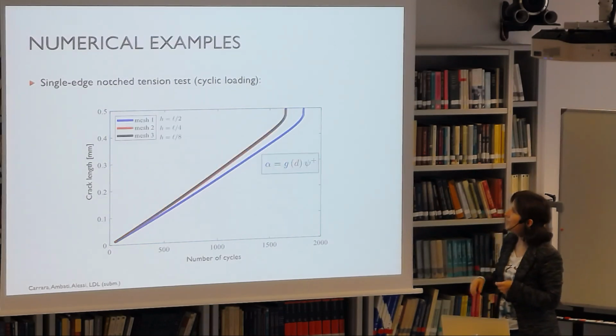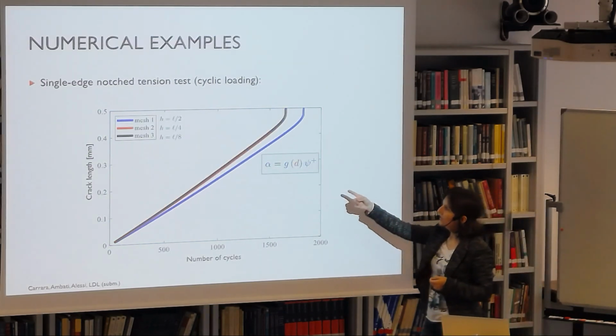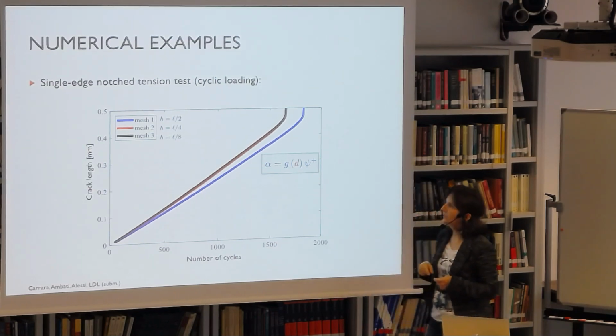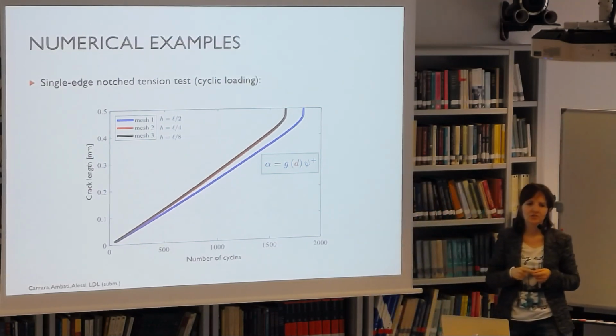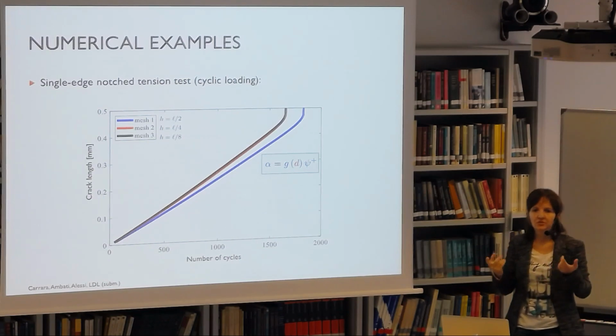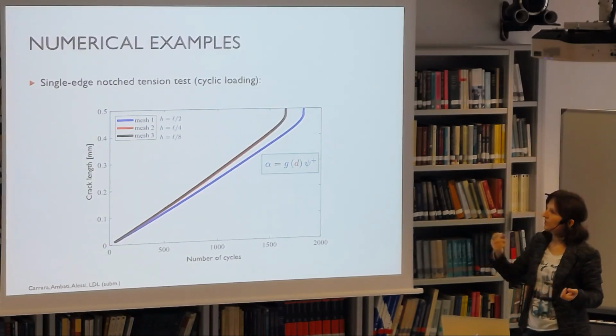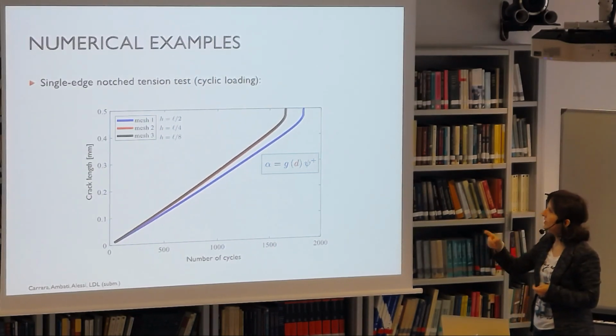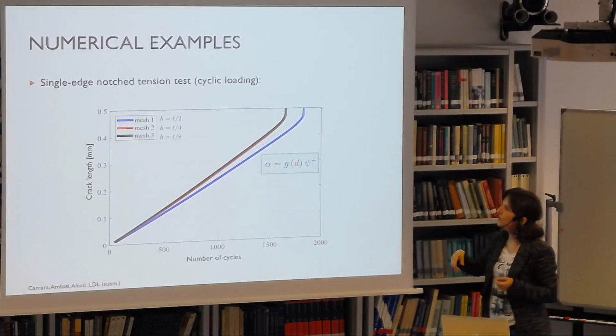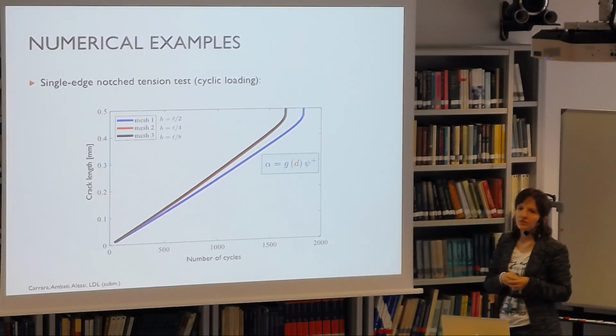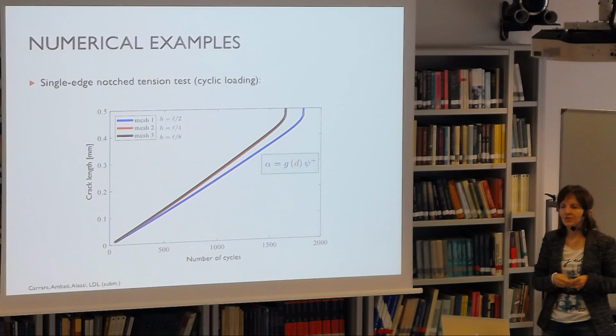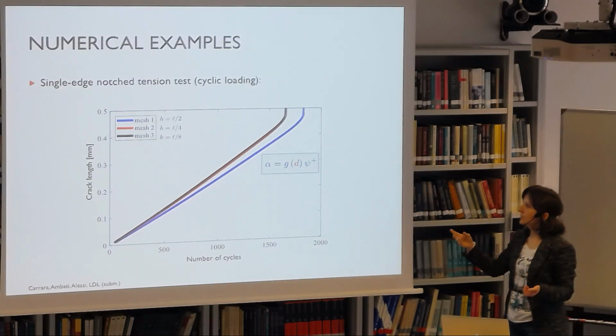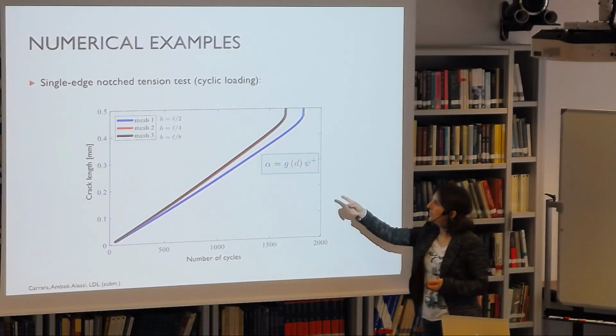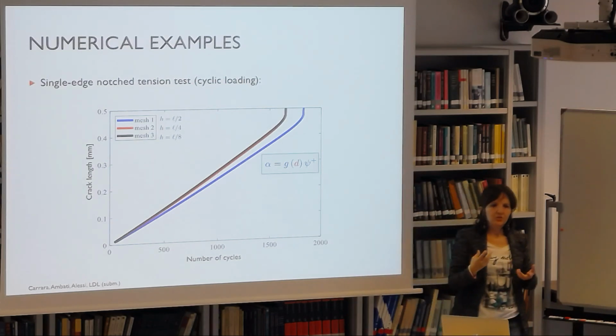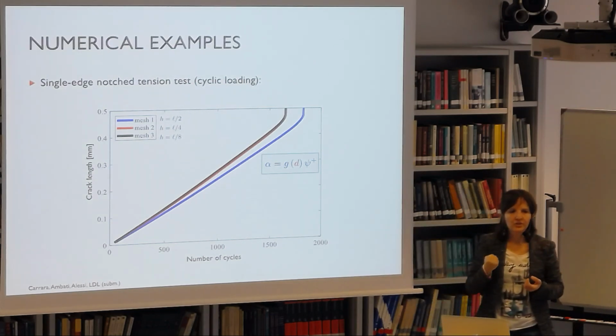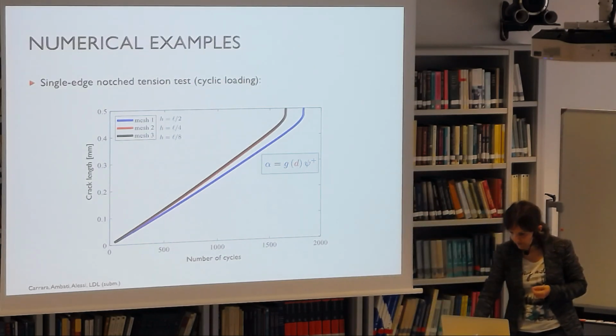But if you use, for instance, as we did, the degraded positive part of the elastic strain energy density, this is a good option, then results are mesh insensitive. So you see here, okay, the first mesh is still too coarse, but the second and third are on top of each other, the results. Another, I'm sure one could also use the stress, some measure of the stress which contains G of D, and so is also not singular.